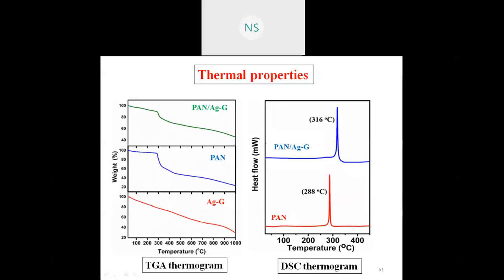And again we have studied, that peak is not shown here, that is a silver graphite nanoparticle. It is showing in that particular range, that means near about say 300 or like this. But because of the complete exfoliation and complete uniform decoration or the porosity of that particular PAN nanofiber, the thermal stability of that particular PAN AGG nanofiber is found to have enhanced property. Next.